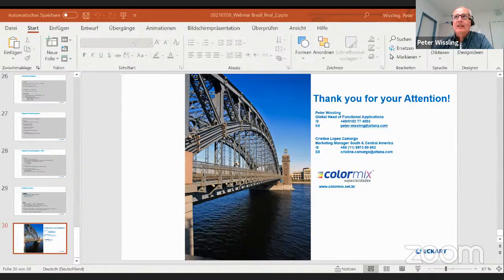Waterborne is a little bit of a topic, I would say, more in Europe, where there is high concern about ecological topics. So we have generated specially pre-treated zinc flakes that give an initial protection against reaction of zinc with water and still keep the corrosion protective performance of the standard zinc flakes. So I would say universal use of zinc flake is possible, and we even have customers using zinc flake in powder coatings. So similar principles as mentioned apply. So yes, any resin system is possible. Any application technology is possible if adjusted a little bit in the formulation.